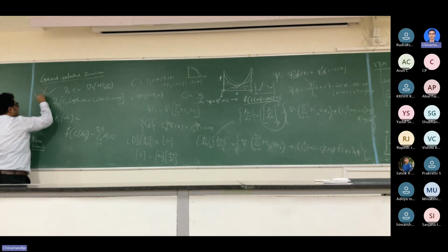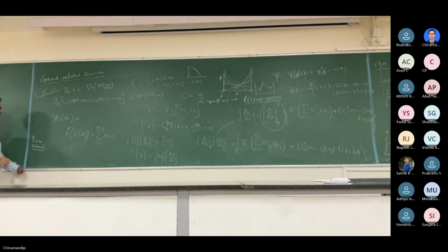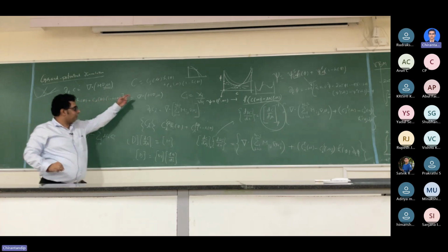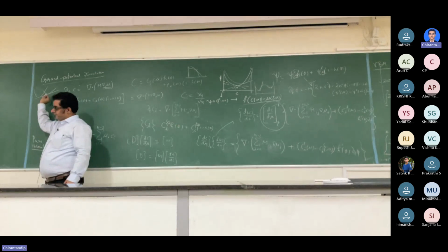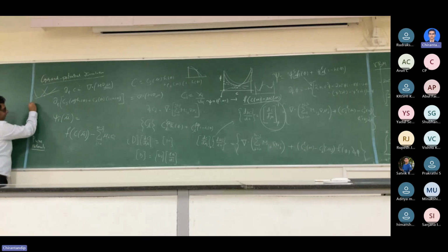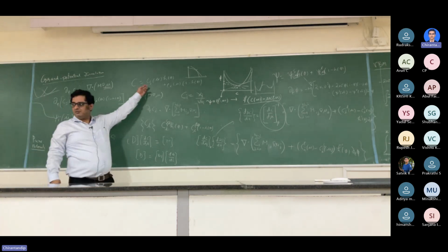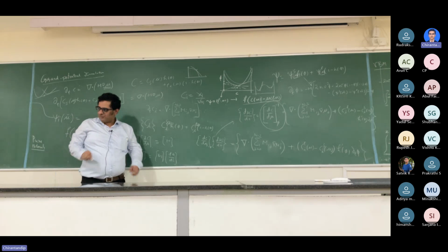So if you are here, and the composition corresponds to a point here, your mu is constant along this line. The mu is not changing. Whatever composition you pick, that is just defining how the composition will vary across the interface from CS to CL. This is the variation. The composition will vary. It's not a sharp interface. The CS will be a function of phi, but that is the function. That's the common tangent line.